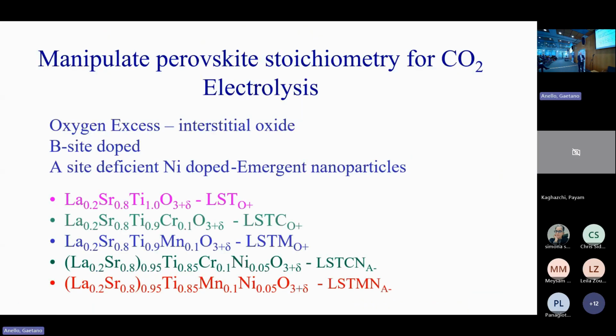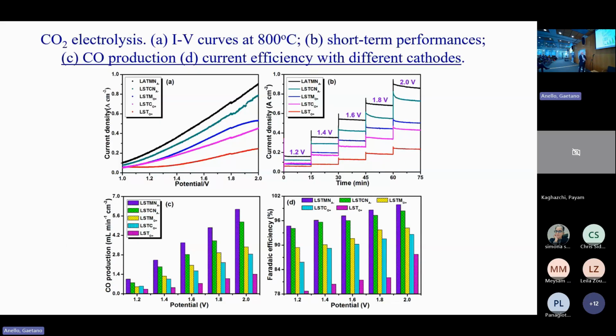So going back to A-site deficiency exsolution, we looked at various compositions. These are 95% dense. This is manganese nickel. This is chromium nickel. These are non-deficient, which are effectively oxygen excess, and we compared these materials. And here again, you get very good CO2 conversion. The one that works best is what we would like to work best, the manganese containing A-site deficiency. Then the chromium one. So the A-site deficiency makes the exsolution much easier, makes the sample easier to reduce, and you get better performance.